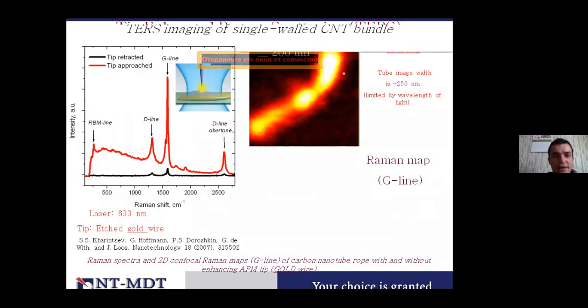Black one is when the tip is retracted from the surface, and the red one is when we approach the tip to the surface and this plasmon resonance effect appears. So the signal is dramatically increased just on the area under the tip.